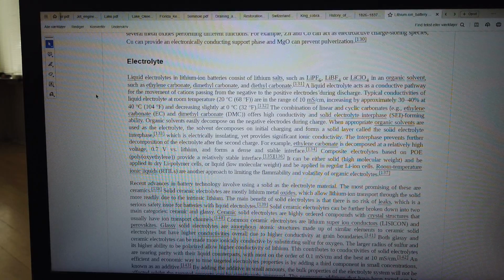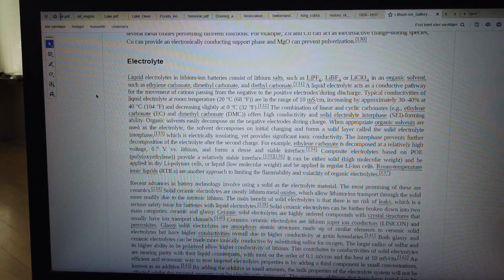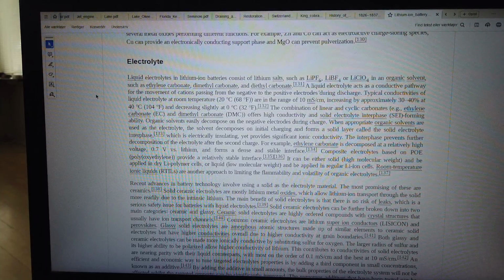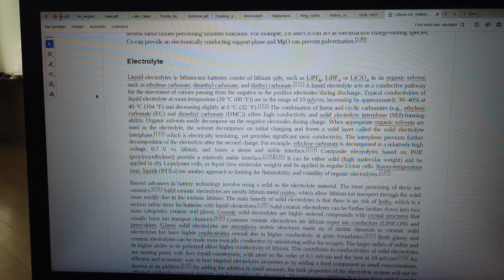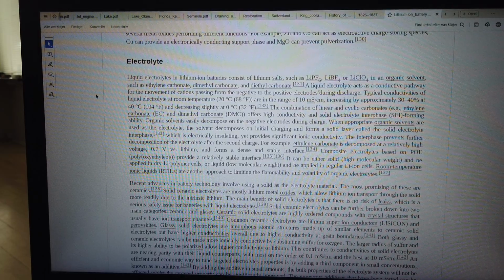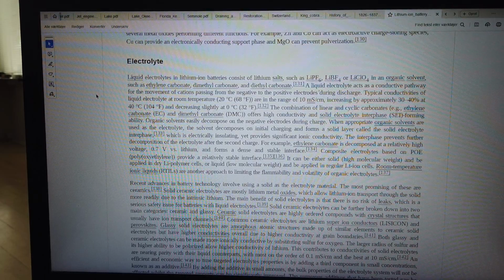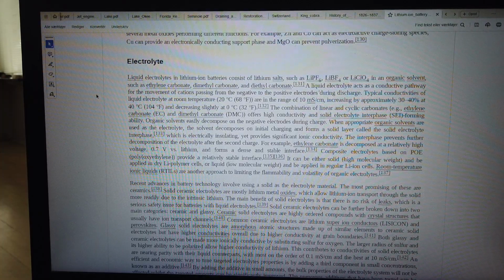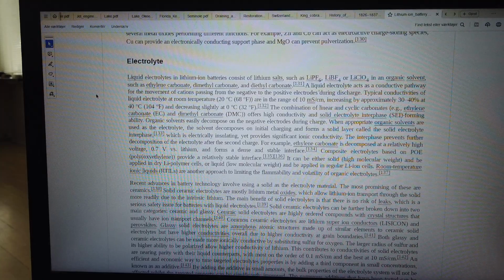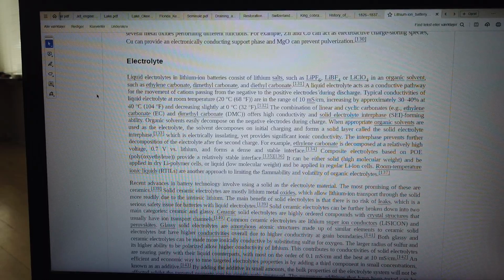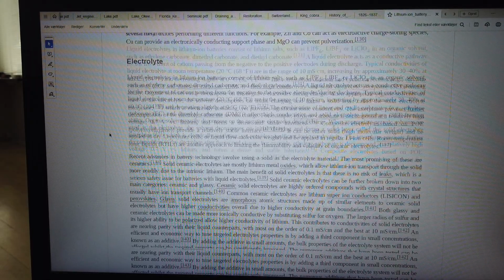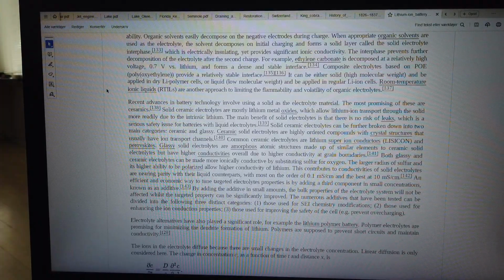132. The combination of linear and cyclic carbonates, for example, ethylene carbonate, EC, and dimethyl carbonate, DMC, offers high conductivity and solid electrolyte interface, SEI, forming ability. Organic solvents easily decompose on the negative electrodes during charge. When appropriate, organic solvents are used as the electrolyte. The solvent decomposes on initial charging and forms a solid layer called the solid electrolyte interface. 133. which is electrically insulating, yet provides significant ionic conductivity. The interface prevents further decomposition of the electrolyte after the second charge. For example, ethylene carbonate is decomposed at a relatively high voltage, 0.7 V versus lithium, and forms a dense and stable interface.